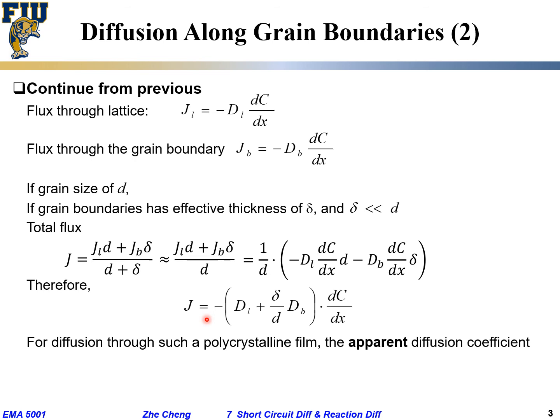For diffusion through this so-called polycrystalline film, for this highly simplified scenario, we introduce the so-called apparent diffusion coefficient, D_app. We just lump these together. The apparent diffusion coefficient for this whole polycrystalline non-uniform structure would be the lattice term plus what? The contribution from the grain boundary, but not the direct addition of the grain boundary diffusion coefficient. It has to be modulated by the proportion of grain boundary, which is delta over D. Typically, delta over D is much smaller than 1. So that's why I cannot add the whole grain boundary coefficient. I have to add it, but modulated by the proportion of grain boundary, which is just the thickness ratio.